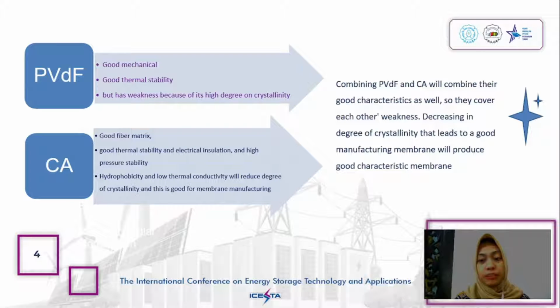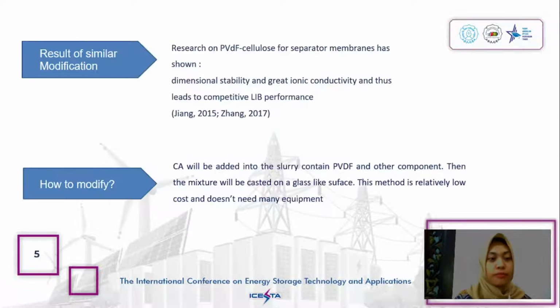By combining PVDF and cellulose acetate, we will combine their good characteristics as well, so they can cover each other's weakness. The decrease in the degree of crystallinity leads to good membrane manufacturing, and we will produce a membrane with good characteristics too, so the performance of the separator can be improved. The results of similar modifications before have shown dimensional stability and good ionic conductivity, and this leads to competitive LIB performance.